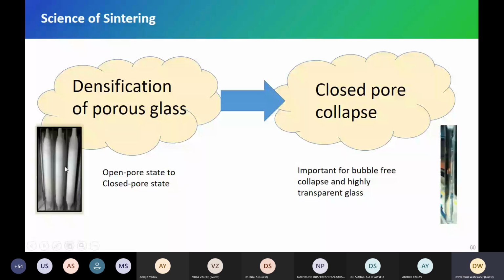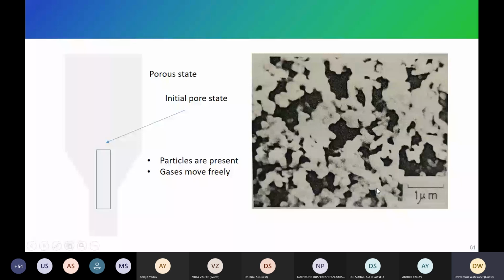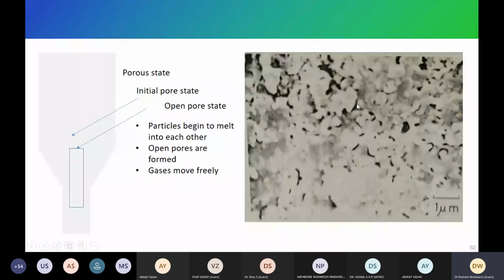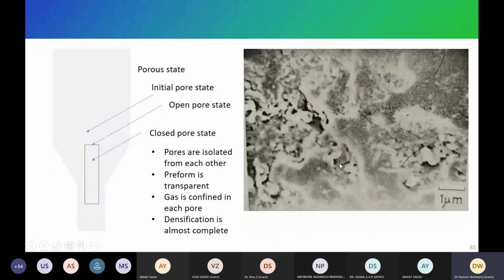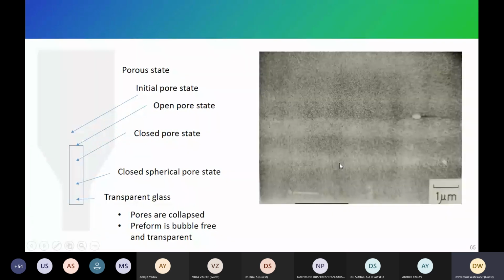As I told you, there are pores. If you take this region, when we have soot, it looks like this way. So there are a lot of pores here. So gas is trapped here. It's very necessary to remove any gas trapped in these pores. This is the microscopic structure of the soot. As you go on heating, these pores are reducing, isn't it? Slowly, all pores are reducing, and finally you get this clear glass. So that is the simple process here that is proved by these pictures.